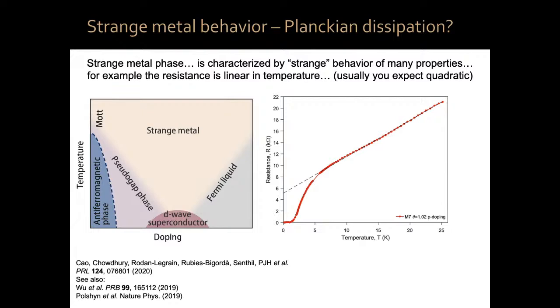As soon as you get out of the superconducting state in the cuprates, the resistivity versus temperature is linear. And here, these are data for magic angle graphene. As soon as you get out of the superconducting state, the resistivity starts being linear in temperature. In fact, we can take a sample where the critical temperature, because we can tune this, is very small, and then it starts to be right away linear in temperature. More recent data from the group of Dmitri Efetov have shown that this linear in temperature behavior can go down to 40 millikelvin.